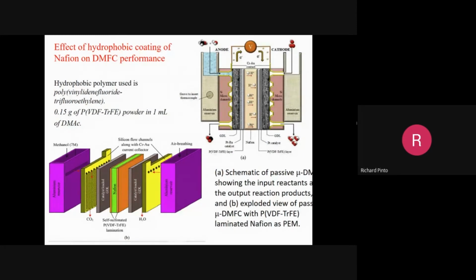We have a Nafion membrane. On the left side we have a coating of PVDF-TrFE, on the right side also, so both sides are coated. This is shown again here. You have the methanol here, and microchannels in silicon for the flow of methanol. Then we have the GDL here, brown is GDL, and then the platinum-ruthenium catalyst to break methanol into carbon dioxide and H plus, and then we have a PVDF-TrFE layer on the Nafion membrane.